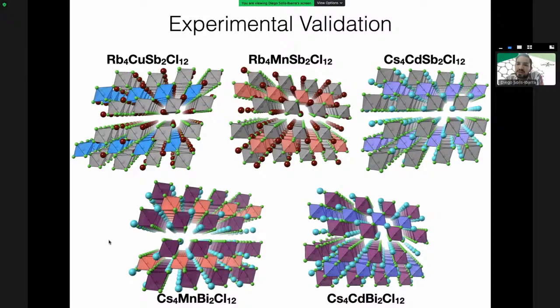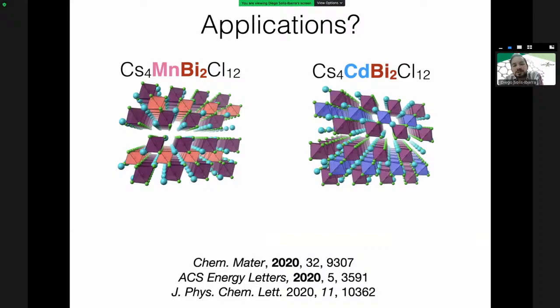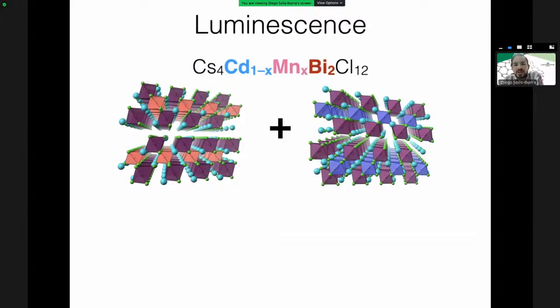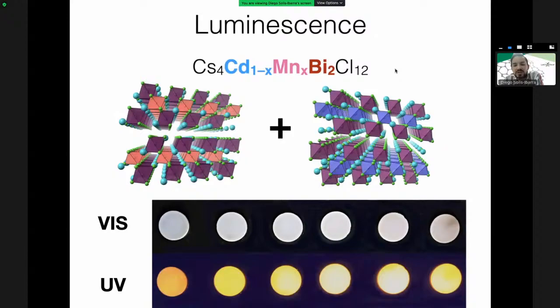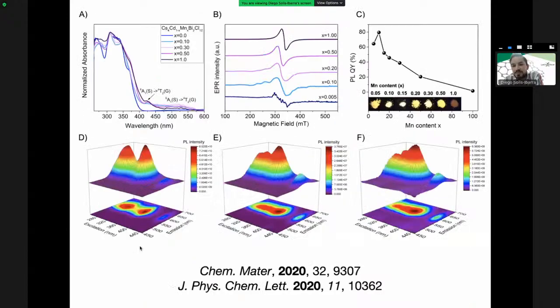So now you might think, why should I care about this family of materials, right? Okay, well, I'm going to tell you a bit of a story about these 2 materials and why we think they could be useful. These 2 materials are some of the ones that I mentioned. They have a similar structure. They have manganese bismuth and cadmium bismuth. And when we combine them, we find that these materials can luminesce very brightly. They show photoluminescence of up to 80%, which is really high, and suggests that they could be used in devices such as LEDs, maybe as phosphors in LEDs, or for other applications.